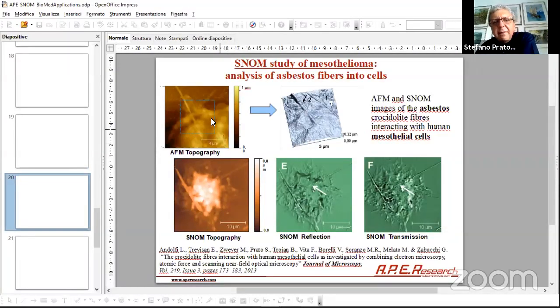The aim of this study was to understand if the small asbestos fibrils were entering into the cell, and if entering into the cell, whether they were entering into the nucleus. So we have a cell, we have the asbestos fibril here. You can see it from the topography. From here, it's difficult to understand if this fibril is here or here. With the help of the SNOM, we were able to see that this fibril is below the surface, but not in the middle of the cell, just a few nanometers below the surface, just by making a comparison between the transmission and the reflection image.